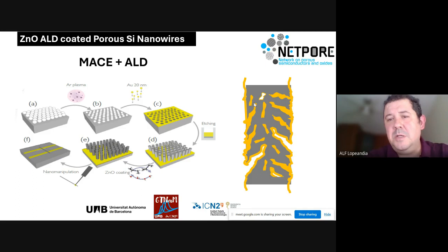The idea was, if we are able to deposit a very thin layer, zinc oxide is conductive, and we can increase the electrical conductivity while preserving, because this will be well below the nanometer thickness, the thickness of ALD zinc oxide. We will be able to preserve the low thermal conductivity. We expect to preserve the low thermal conductivity of these wires. Okay, that was the idea.